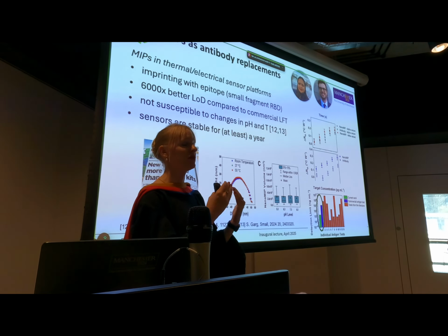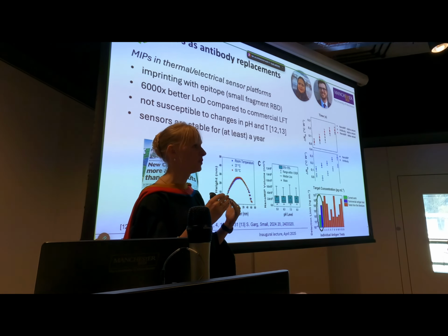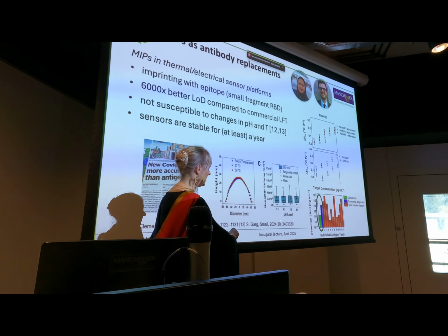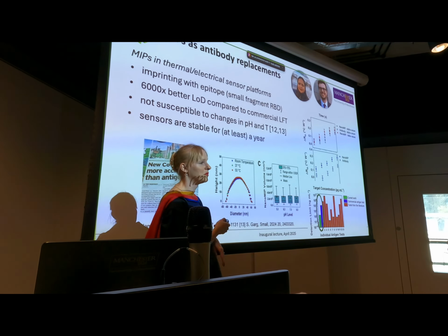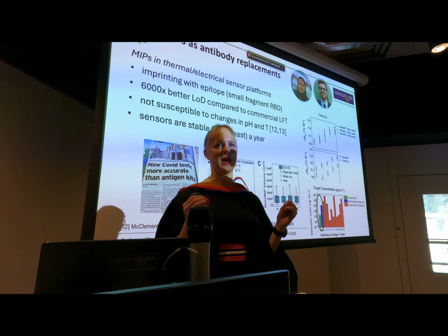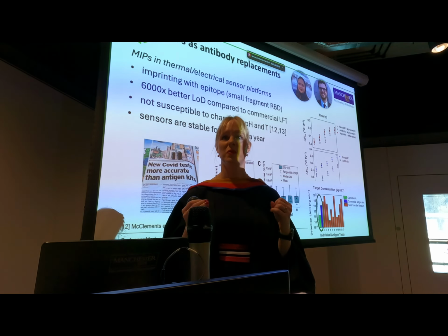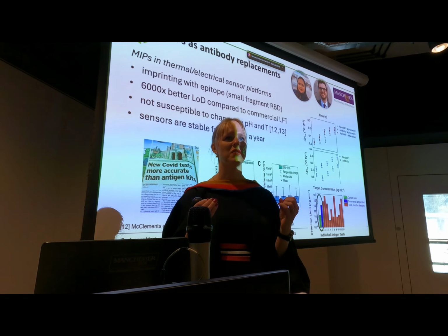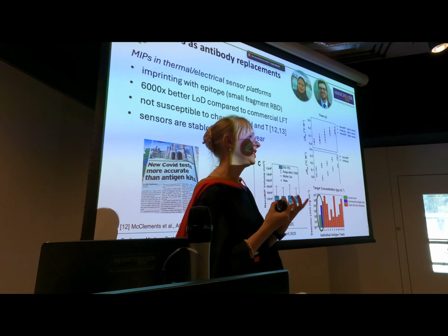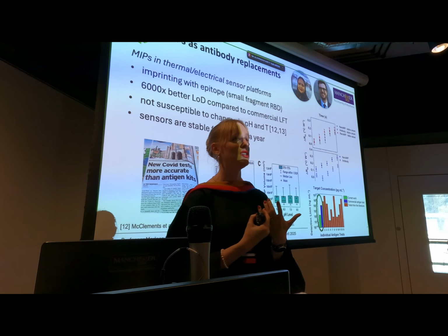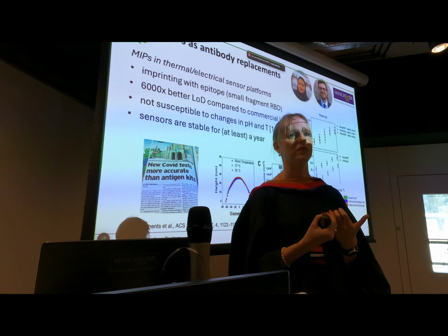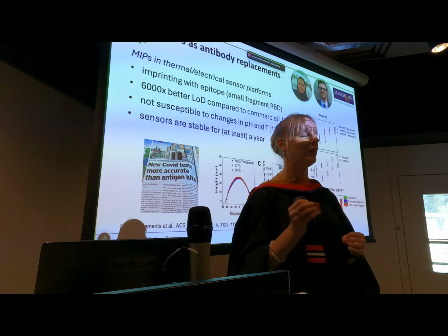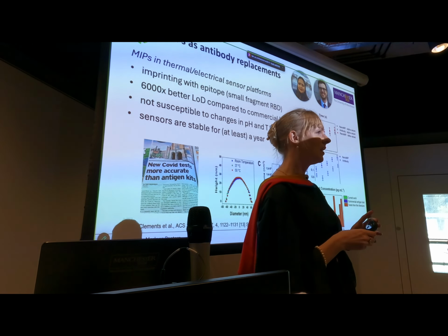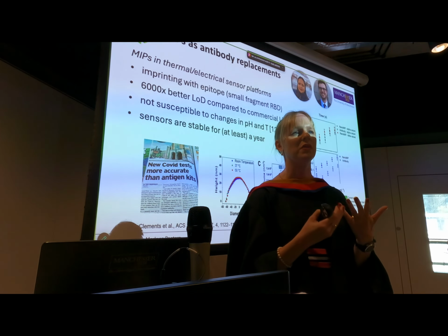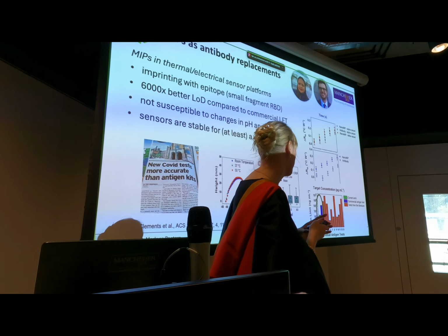And later on, we could also see that nothing was really changing in terms of the performance. Similar to the pH, we took quite a broad pH level, and you could see that the volume was really not changing that much. So in essence, we were able to measure all these things without having these false positives, or potentially without having that complicated buffer solution. We'd just take your swab sample and you could directly measure it. And this could open up opportunities, for instance, if you wanted to measure saliva or other things.